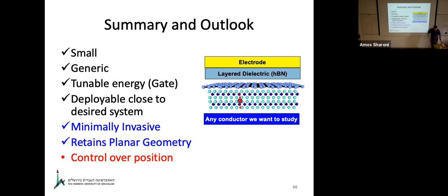And since I didn't show you the graphene data, that's actually quite important because now you have an SET which is 1 nanometer away from something else. That means it's extremely sensitive to small variations of the electric field. And there are various interesting things you can think about of what you can study if you have an SET which is a nanometer away from something else.